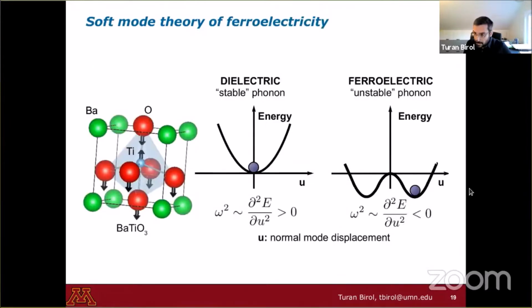So in a real material, of course, we don't have just one-dimensional materials like the one I showed you. We need to take into account a three-dimensional displacement pattern of all the atoms. So, for example, barium titanate, what I show here, is a prototypical ferroelectric where, say, the bariums are more or less stationary, but titanium and oxygens are displaced against each other to create this polarization. And this type of displacement is what you would call a phonon displacement in undergraduate solid state physics.